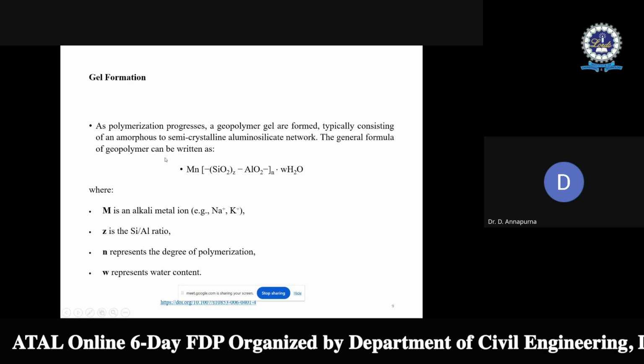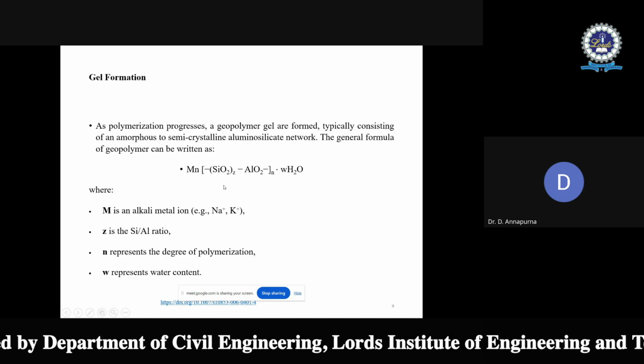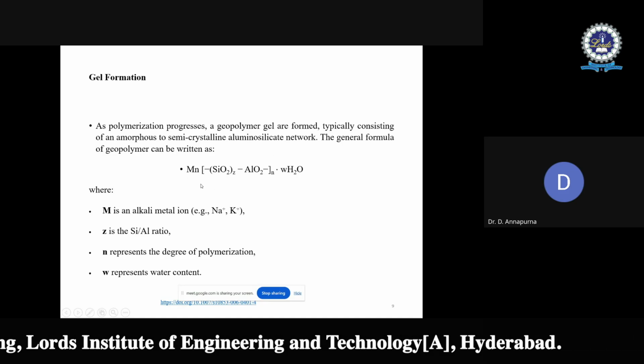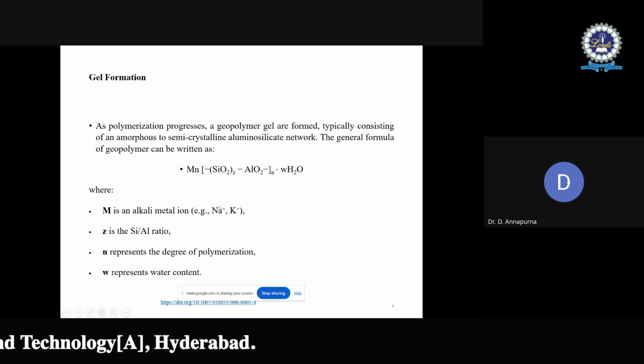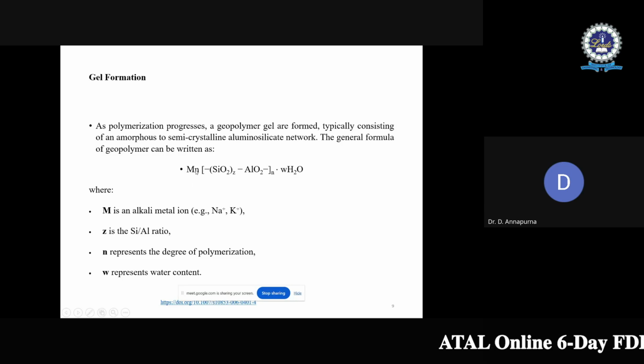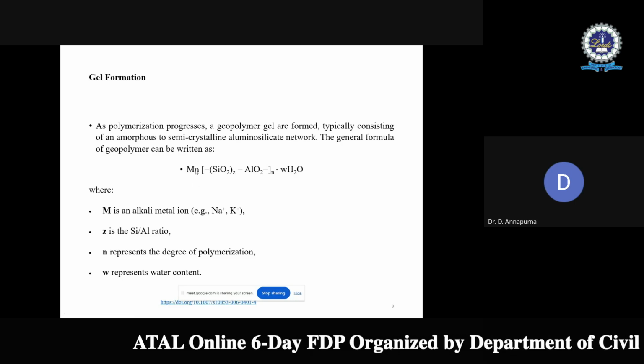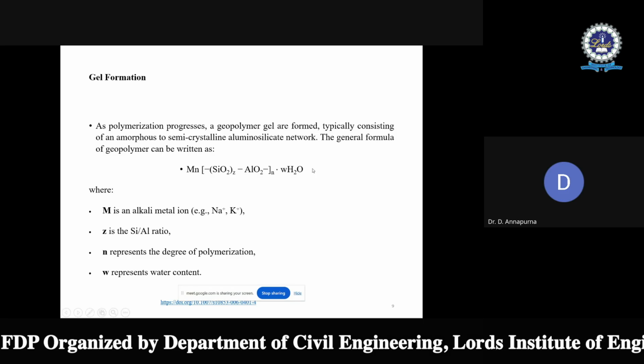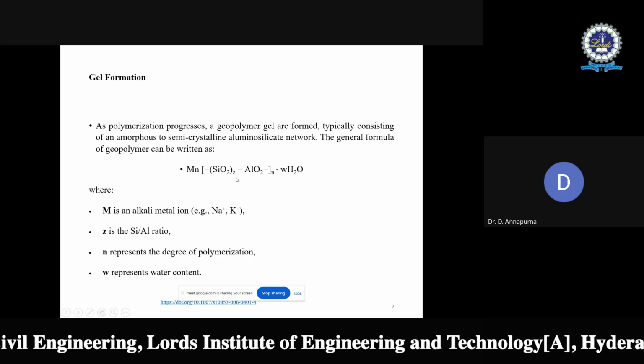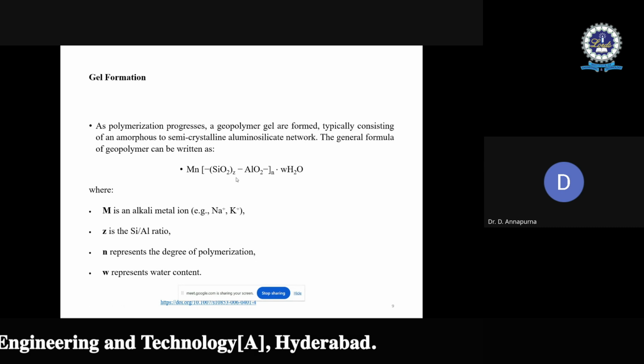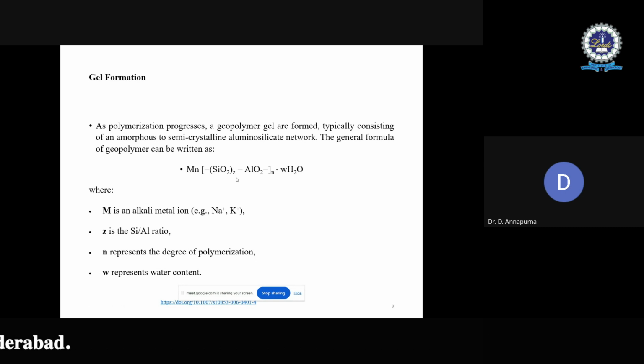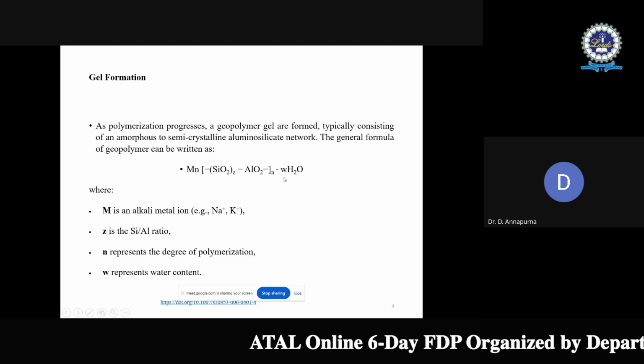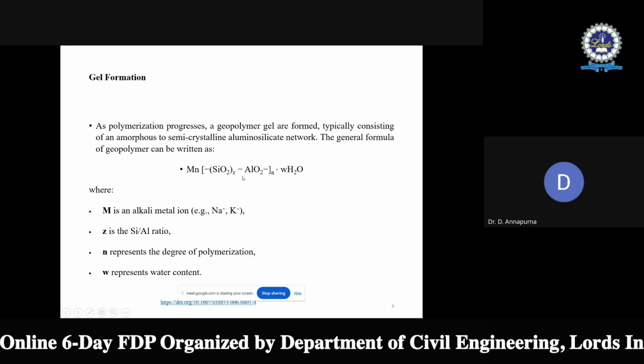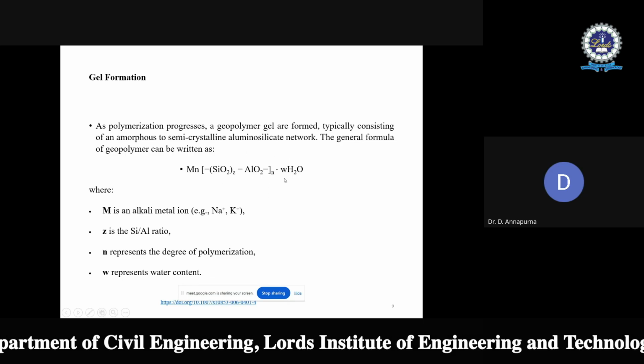The general formula of geopolymer, if you look at it, is where M stands for alkali metal ion, maybe sodium-based alkali activator or potassium-based alkali activator, whichever you use. And N represents the degree of polymerization, how much polymerization has occurred. And Z stands for the silica by alumina ratio, which plays a very important role in geopolymerization. If the silica by alumina ratio is between 1.5 and 2, then the geopolymer product will be produced. And W represents the water content in this particular geopolymer gel. The geopolymerization product will be represented like this.